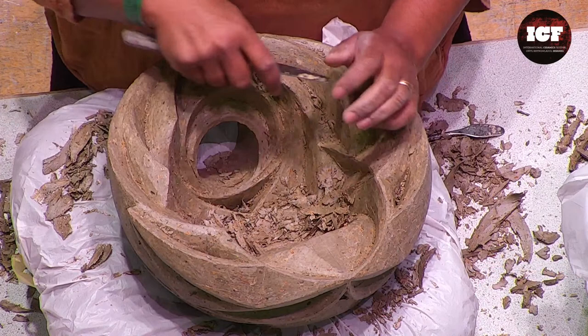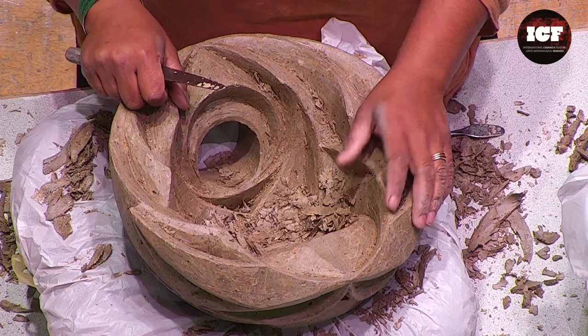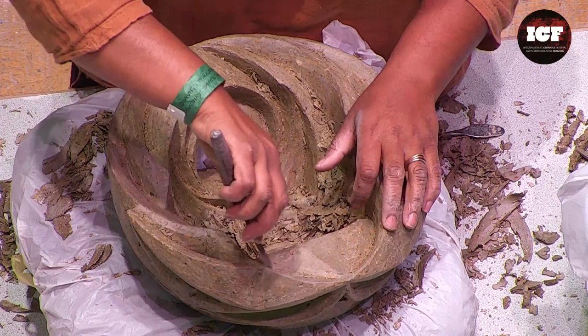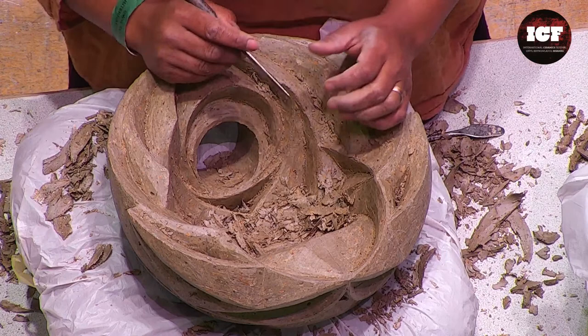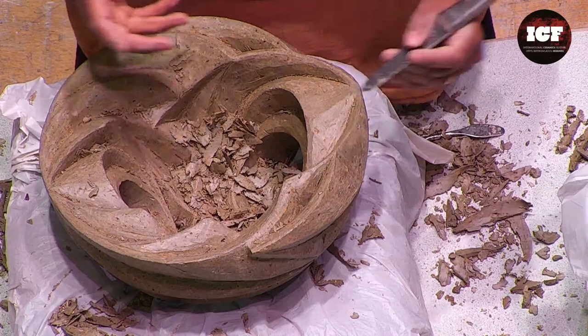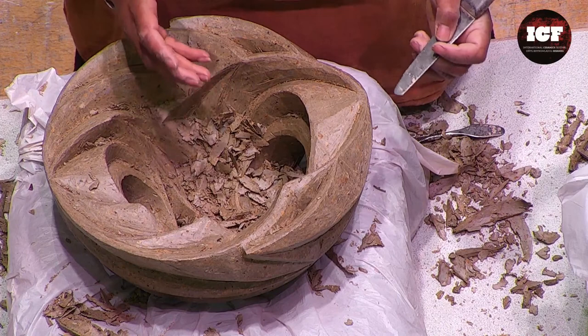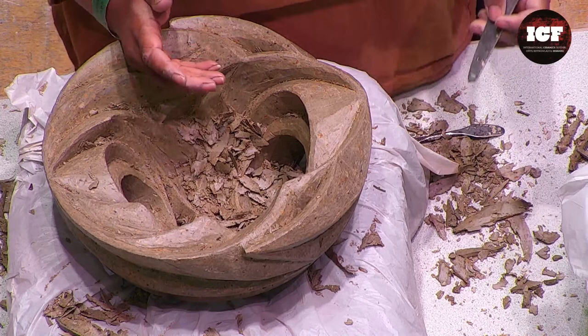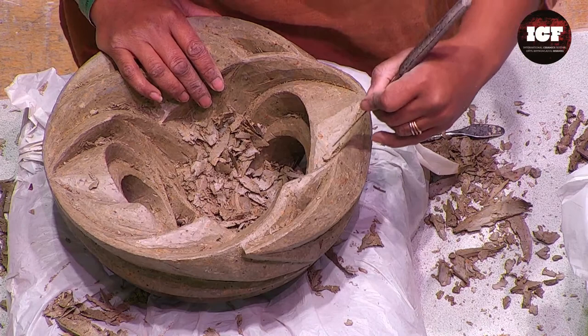I fire at something like 20 degrees an hour? Actually 10 degrees an hour to the first hundred, and these ones probably 10 degrees as well because there are a lot of impurities in the clay. You don't want to take any risk of blowing up or cracking — especially if you've spent months carving. Some crank clays are very forgiving, but some of these clays are not forgiving at all. I vary the firing temperature based on what I think the clay would take, to make it as strong as possible.